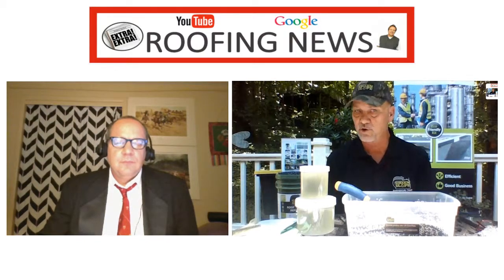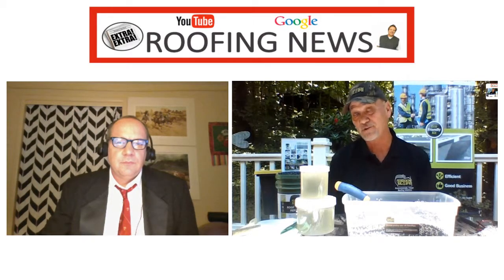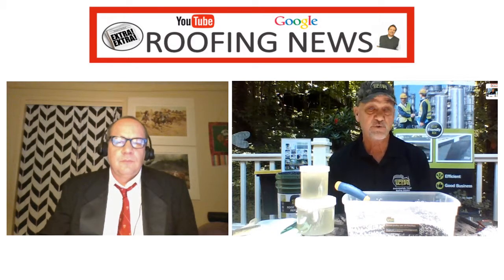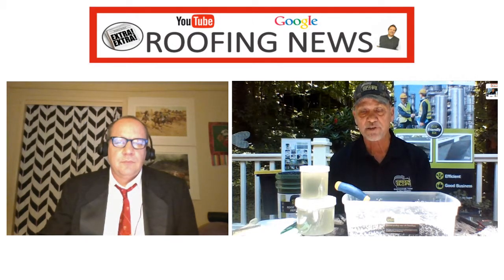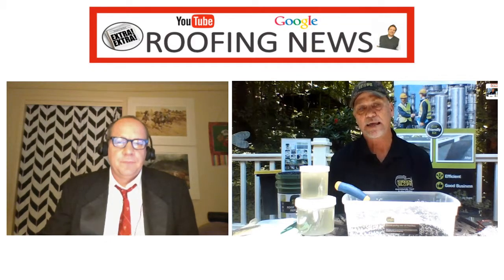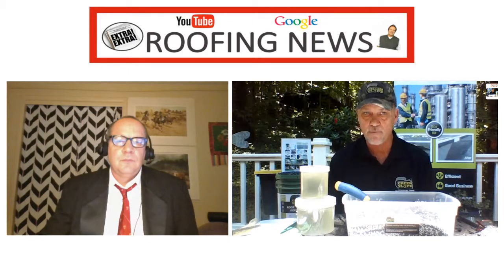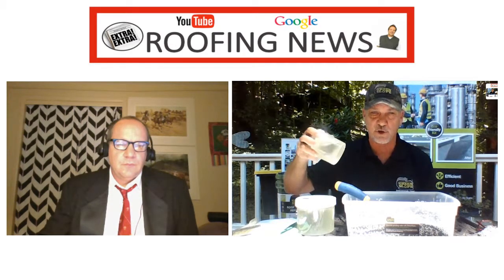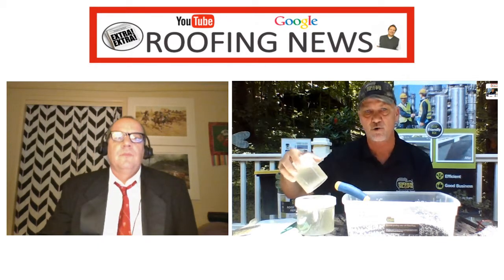This will set up similar to what you might see on a track and field surface. That's about the closest thing I can come to describing it, and you'll find it in any climate. We've put it down in 5-degree weather up in the northern climates just to test if we had any long-term problems, which we did not. It was easy to work with at 5 below because we had the product warm. If it's cold, your adhesive and primers are going to turn thick like molasses and be hard to work with.